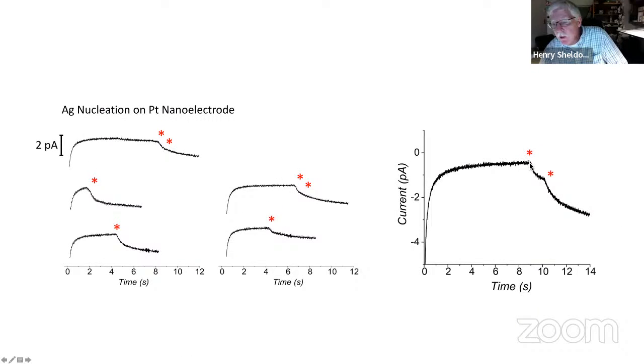Sometimes you get a nucleation event and you get another nucleation event on these small electrodes, all right? This is very infrequent. Most of the time you just see one event here. I don't mean to have 2 red stars, that was a PowerPoint error. There should just be 1 red star here, not 2, because there's only 1 nucleation event. But here there's 2 nucleation events.